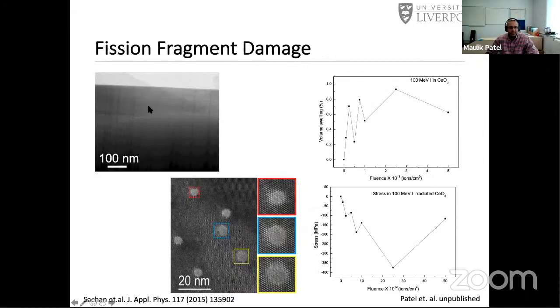You can see in micrographs these tracks, and if you do atomic scale transmission electron microscopy, you can get an atomic resolution image of these tracks over here. I'm trying to point out the bottom left micrograph. This is taken from an oxide called cerium oxide, and these ion tracks are from single fission ions going through these materials. What that does to macroscopic properties is that you have a huge volume swelling that leads to residual stresses in materials. And when you have residual stresses, it's not good for operation.